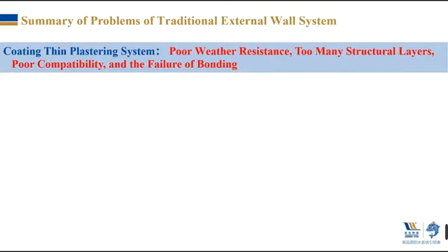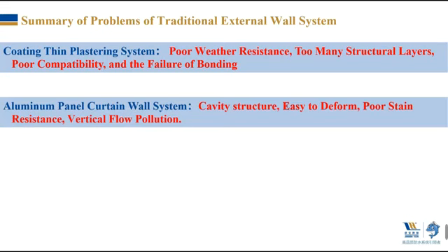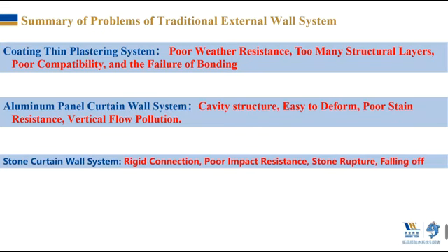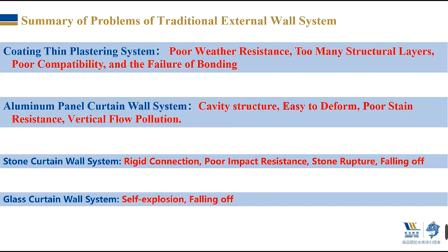To summarize the problems that exist in these traditional systems: for the coating plastering system, the coating has poor weather resistance, and the surface layer is easy to crack. The system has many structural layers with poor compatibility, and the failure of bonding leads to the structural loss of the system. For the aluminum panel curtain wall system, there is a cavity structure in the middle without supporting materials, so the aluminum panel is easy to deform. Also, the aluminum panel has poor stain resistance and is easy to get vertical flow pollution. For the stone curtain wall system, the facing layer is poor in impact resistance, and the stone is easy to break and fall off. For the glass curtain wall system, there will be self-explosion, falling off from the external wall, etc.